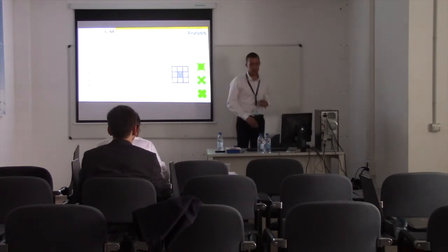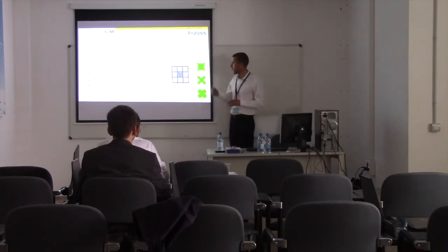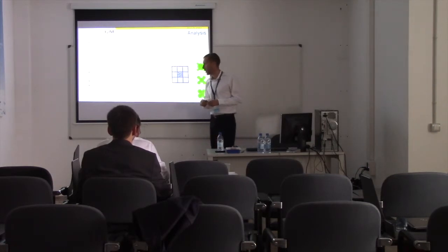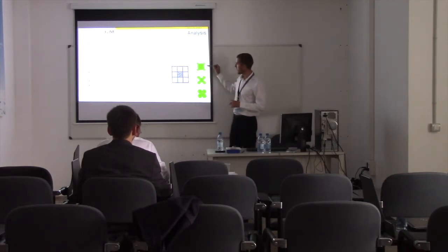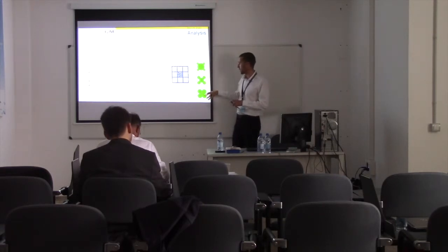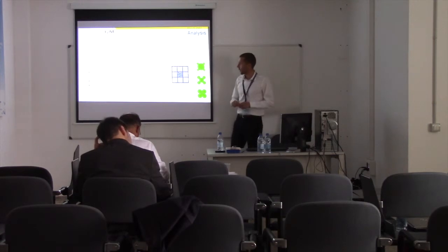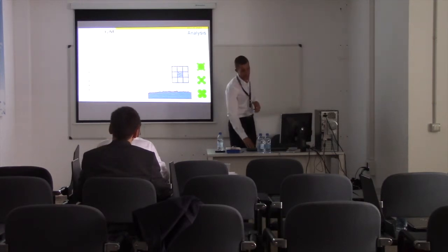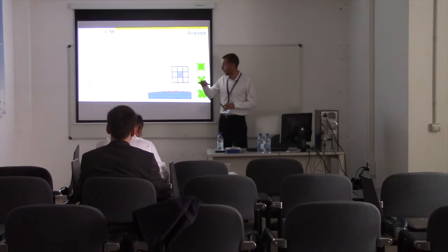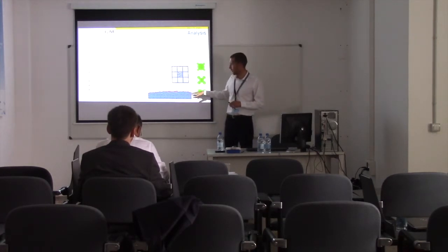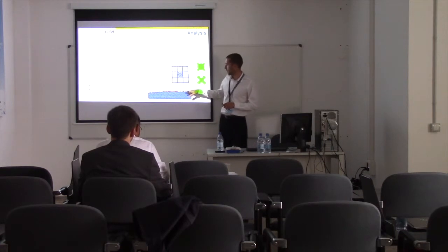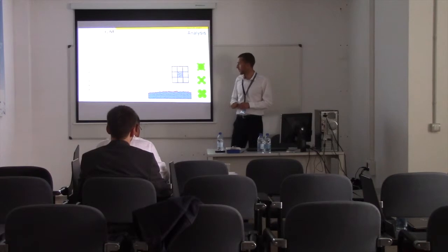We also calculate the coordination number, which is the number of contacts between each particle. Associated to the packing density, we can have an idea how the particles interact with each other and how it is packed in the powder bed layer. And finally, we also evaluate the specific roughness, which is the mean difference of peaks and valleys from the mean height of the powder bed layer.